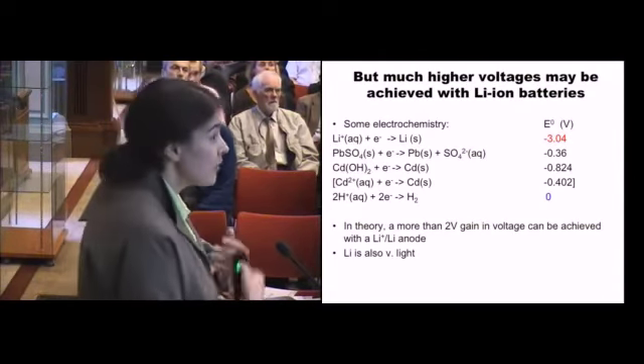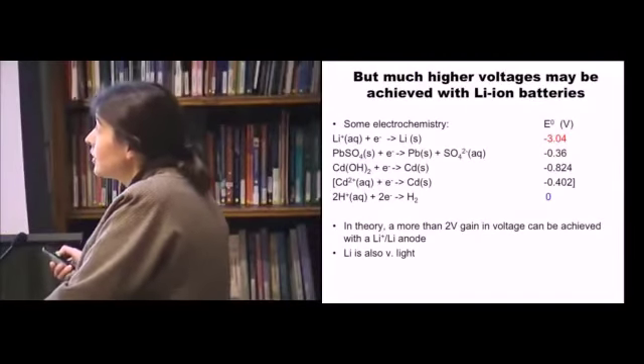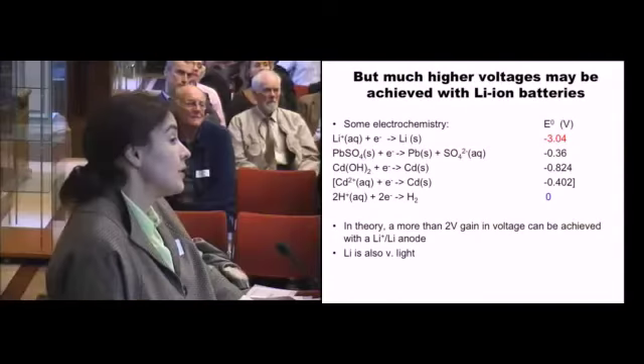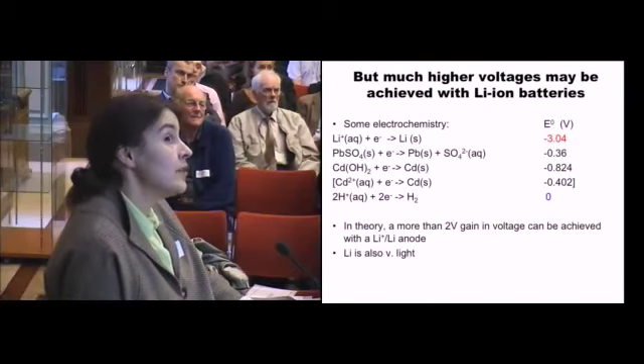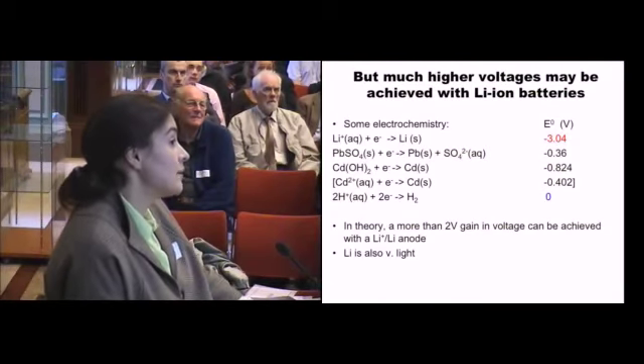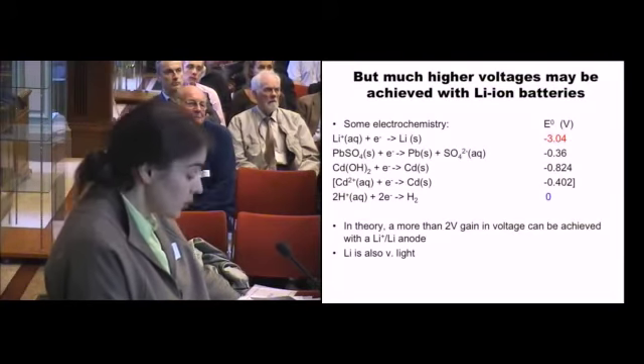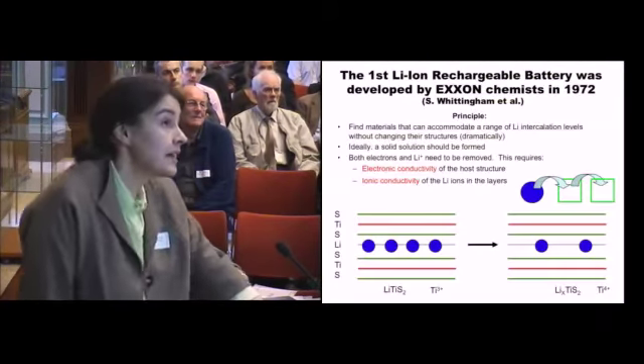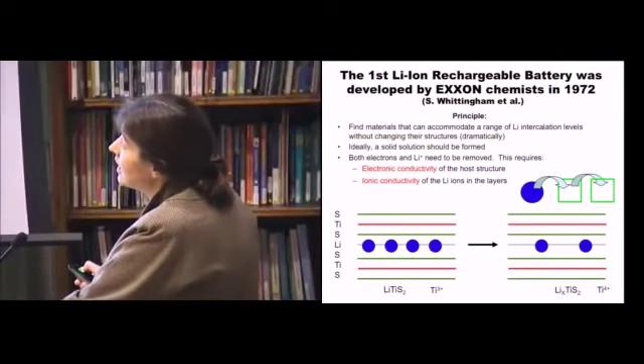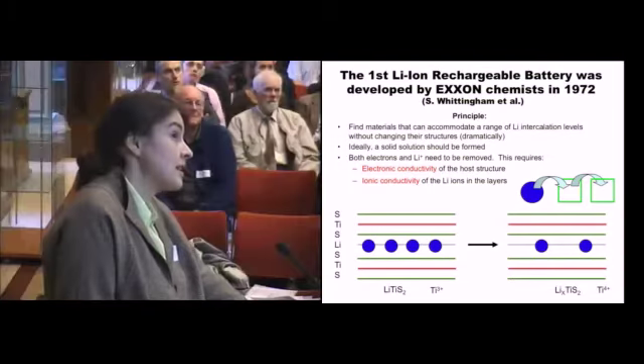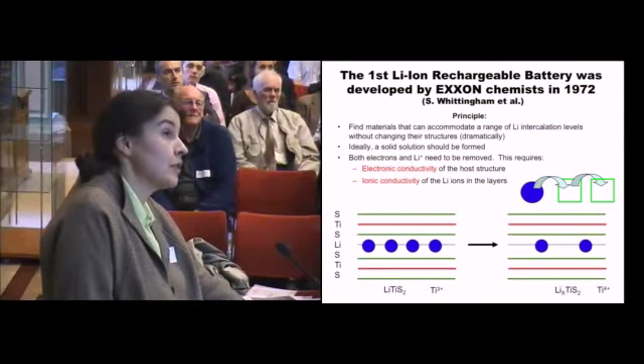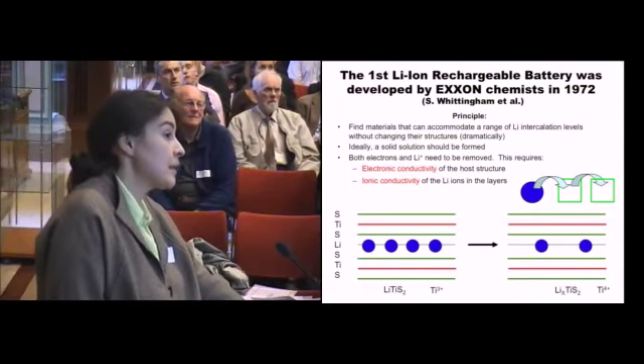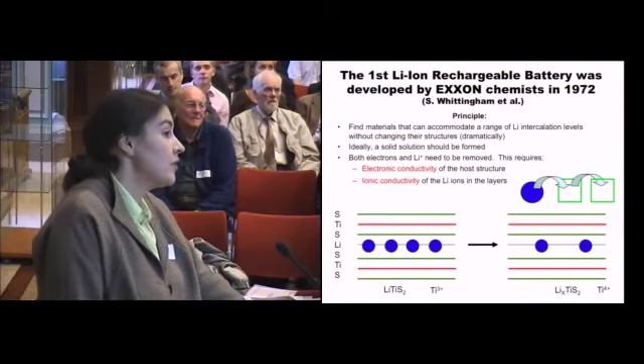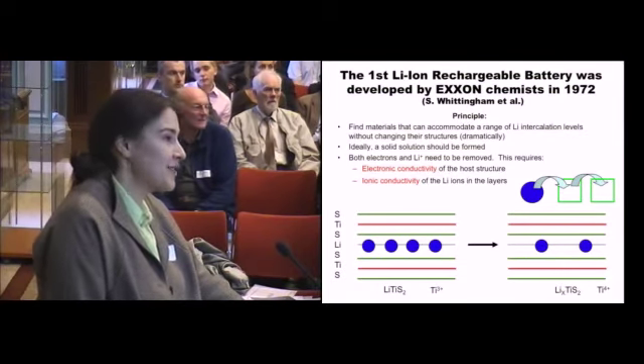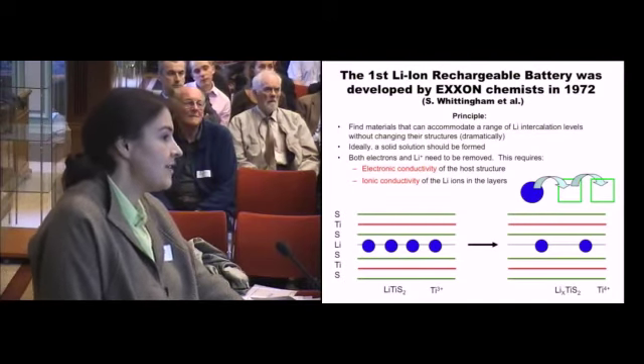So if you think about how you would get a better, higher voltage system, you move to a more reactive element, a more electropositive element like lithium, and you can get almost a 2-volt increase over lead chemistry and cadmium chemistry. And of course, lithium is very light. So in the 1970s, the chemist at Exxon in the US, Stan Whittingham, who was actually trained in Oxford, put together the first lithium-ion battery. He took a layered material, consisting of layers of sulfur, titanium, and sulfur, and then lithium in between them.